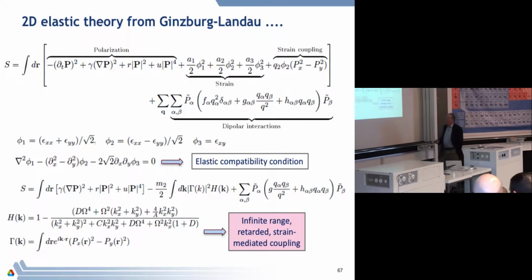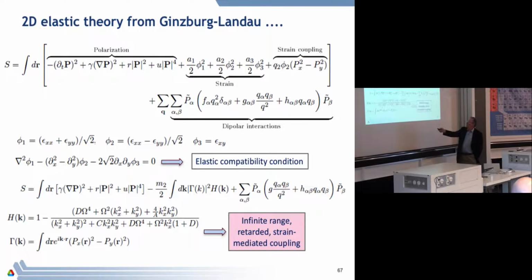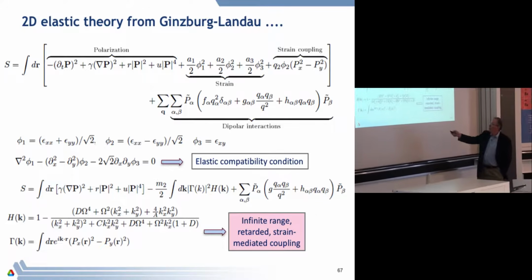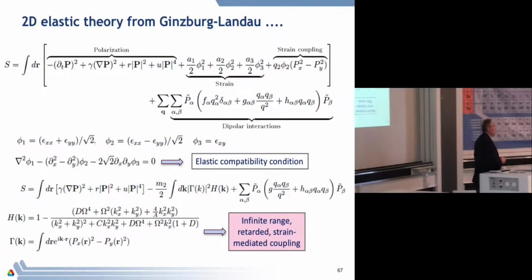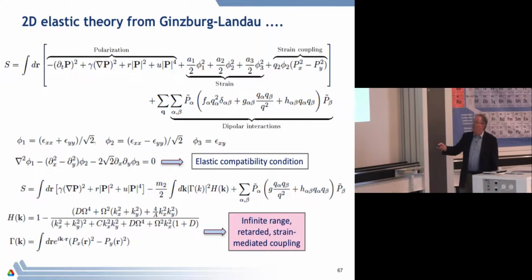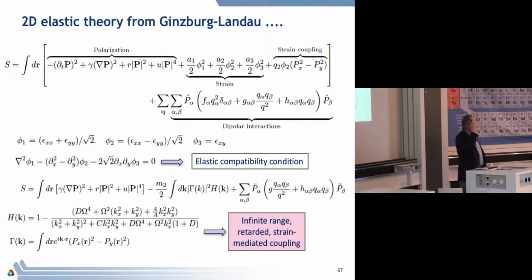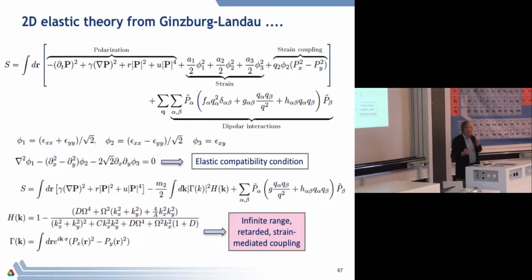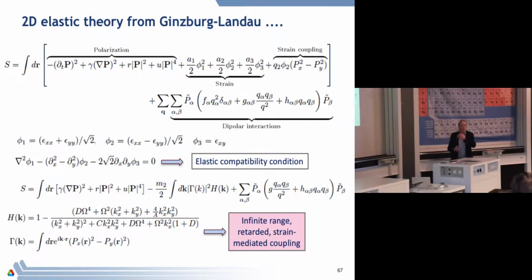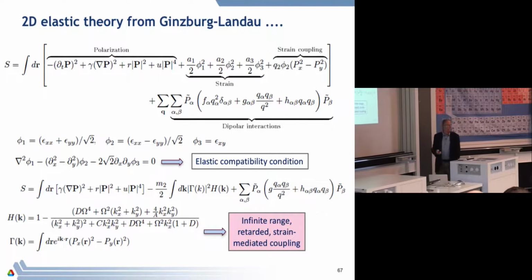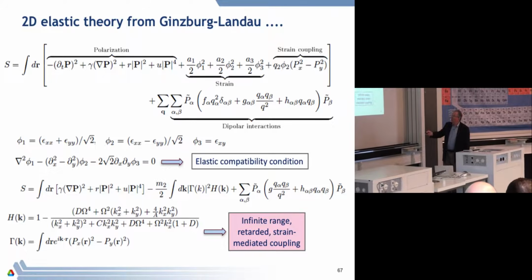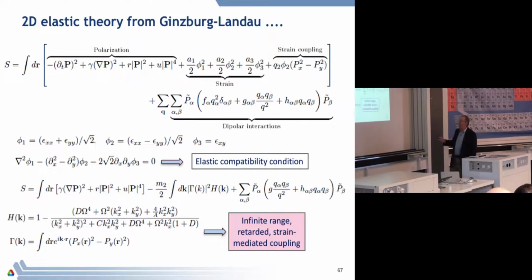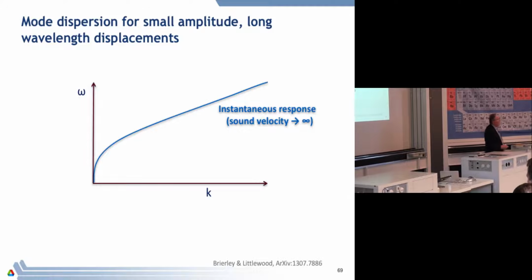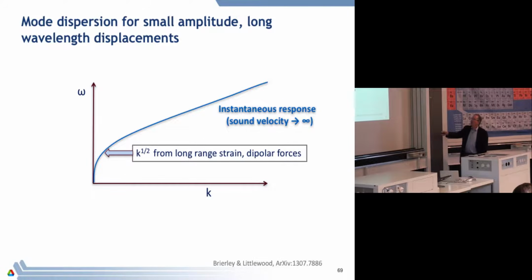Okay. What's interesting to notice if you look at this is that there are as many powers of k on the top as there are in the bottom. Okay. So this is formally of an infinite range interaction. Very different from this thing which is entirely local. Okay. So infinite range interactions do weird stuff. Okay. It's very anisotropic because it depends on the direction that kx and ky go to infinity. Okay. So what would the mode dispersion look like? Well, it turns out that I told you should expect something which was a sound wave, but actually it turns out that it's k to the one half.